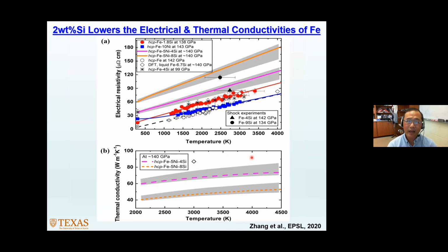All right, so now let's look at the electrical and thermal conductivity of iron alloys, iron-silicon alloys, at high pressure and high temperature conditions. So this figure here is probably a bit busy, so bear with me a little bit. The open circles here are the HCP iron data that I mentioned earlier. So electrical resistivity goes up linearly with increasing temperature. And even for iron-nickel alloy, it also goes up quite linearly with increasing temperature. But for iron with about 2% silicon, the resistivity increases.